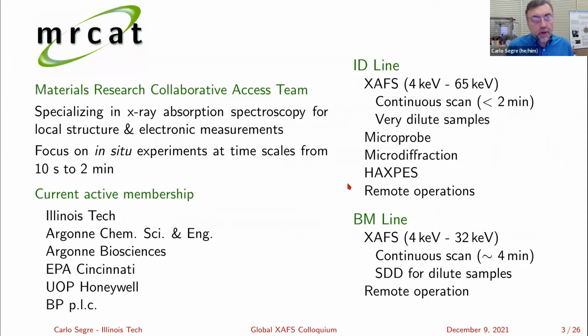So this is my self-promotion. I run the Materials Research Collaborative Access Team. It specializes in X-ray absorption spectroscopy and does electronic measurements and local structure measurements. Our focus is in situ experiments. Right now, we're probably like 1 minute for a standard XAFS, and we can go quite a bit faster than that for our XANES at the insertion device line, where we can go from 4 kilovolts to about 65 kilovolts, and we can do continuous scanning. That's our standard operating method.